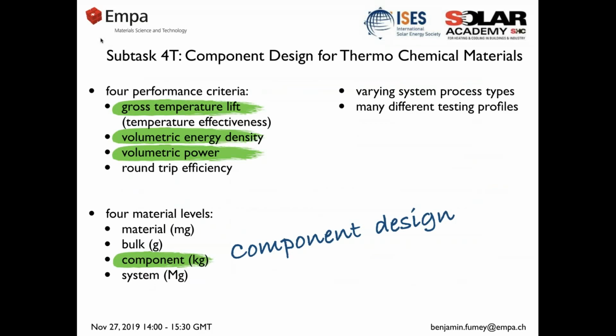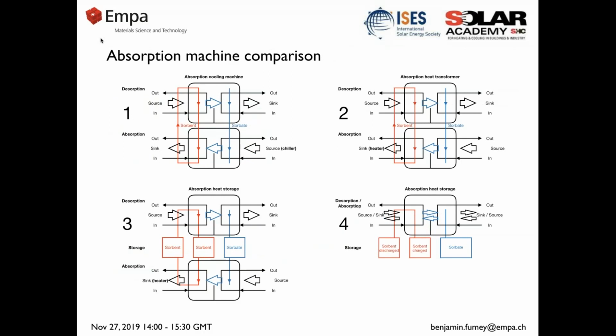Now, with this in mind, going to component design, in our liquid absorption heat storage, we find that this is a similar process as, for example, a chiller or also a heat pump, absorption heat pump. Nevertheless, with including the storage, in other words, the storage of concentrated sorbent and sorbate in charged state, and then discharged state storing of the diluted sorbent for recharging, we have a process where we need to be able to reach this maximum discharging in a single pass of the sorbent through the heat and mass exchanger.